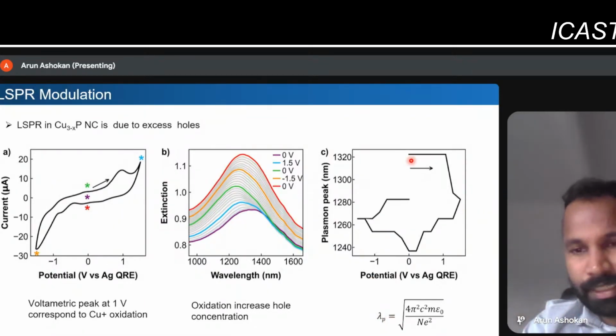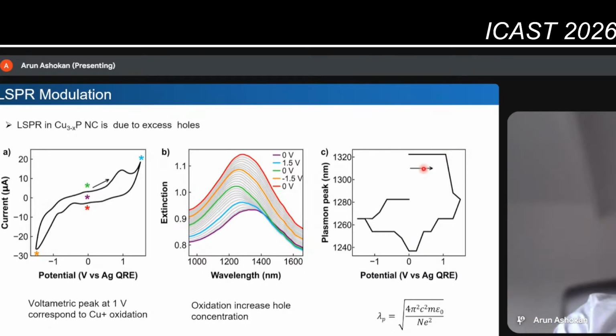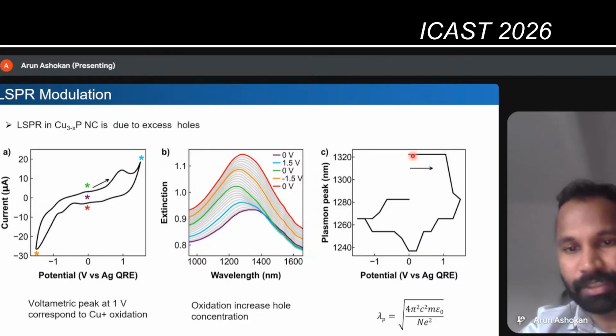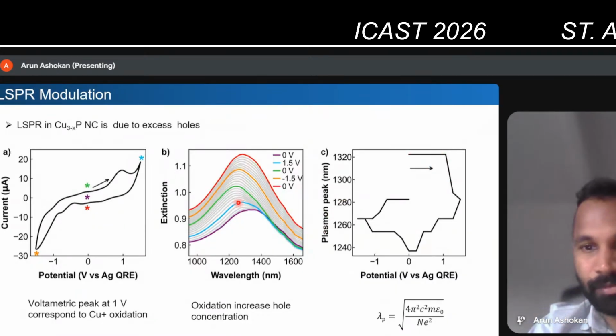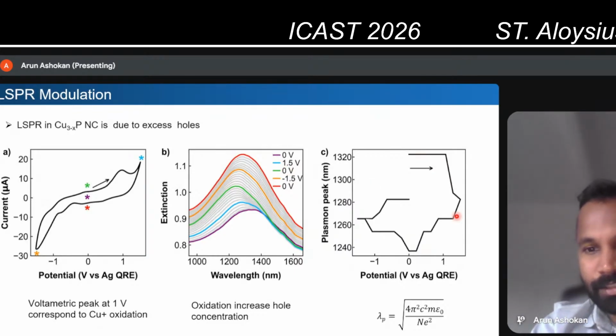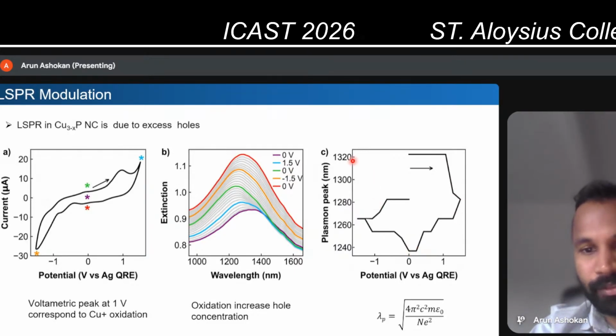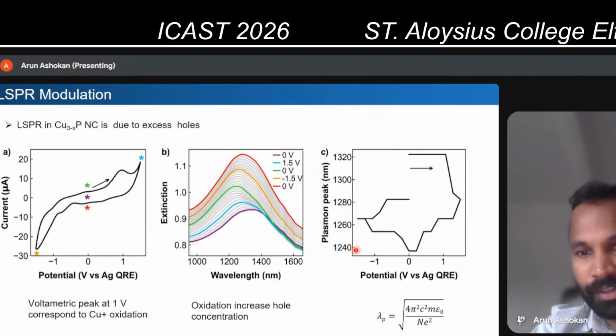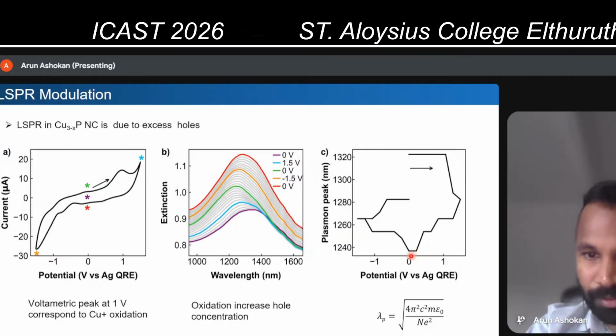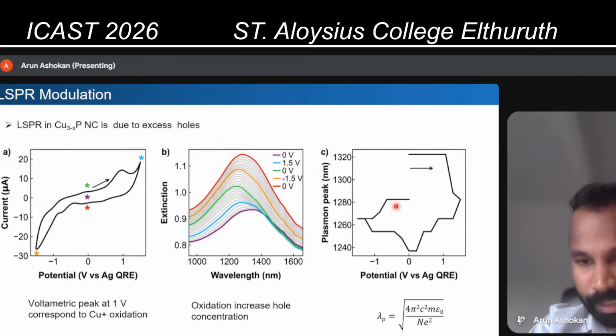So this is basically a plot of potential versus the plasmon peak we extracted from here. You can see that when you oxidize, it's blue shifting all the way from 1320 to 1240 nanometer, and when you're reducing it, it's switching back from 1240 nanometer to 1280 nanometer.